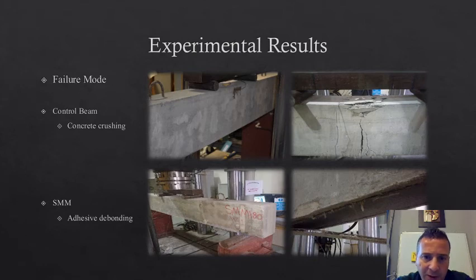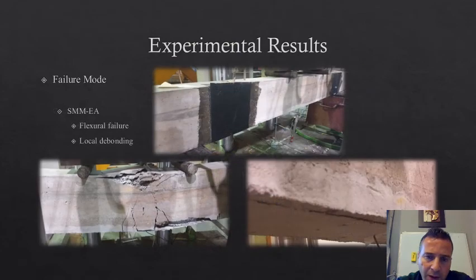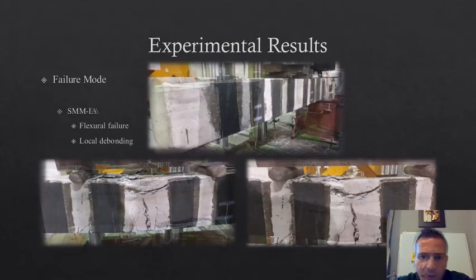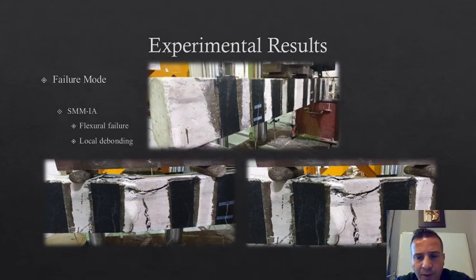You can see here some of the specimens. This is the control specimen. It failed by yielding of the steel reinforcement in conventional flexural failure and concrete crushing. And this one is with the end anchors. Now, let me show you the one without anchors. It failed by debonding. And this one with end anchors fails by flexural failure, by yielding the steel and concrete. And this one is with the intermediate anchors. The one that is not anchored failed by debonding of the sheet from the concrete surface. And here you can see yielding of the steel reinforcement and concrete crushing, and you have some local debonding between the sheets.